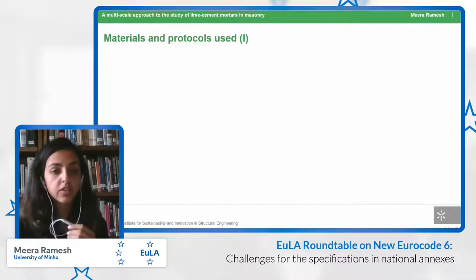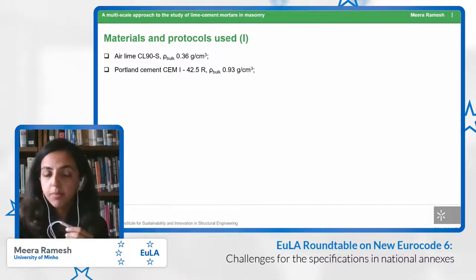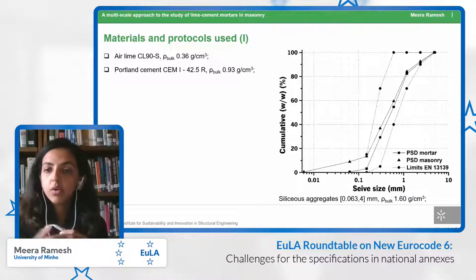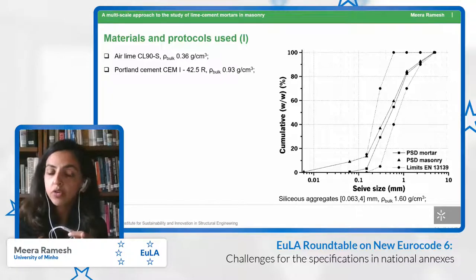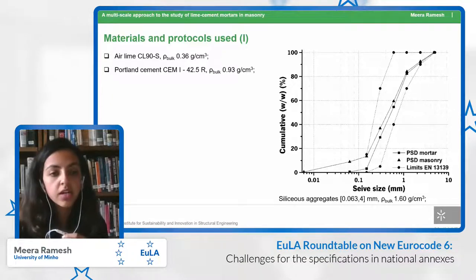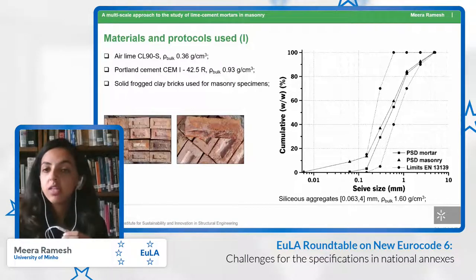The materials that we used for this research were Air lime, CL90-S, and for cement, we used cement type 1. The particle size distribution of the aggregates was determined on the basis of the limits set in the European standards. It was a silica-based sand, and it had particles ranging from 63 microns up to 4 millimeters. And the unit that we used, as I mentioned, was a molded solid clay brick, and it also had frogs in it.